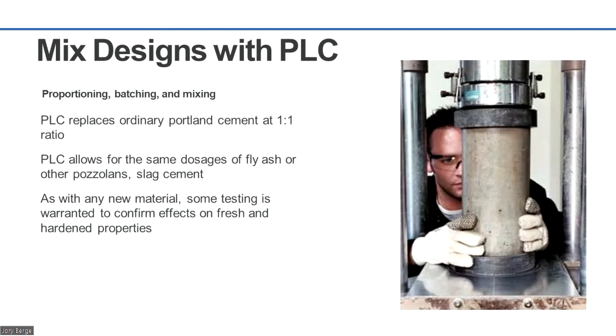And the replacement level is not like using an SCM. It weighs the same, 3.15 specific gravity. We're looking at very similar mix designs with a 1-to-1 replacement ratio. So this typically allows for the same values of fly ash and values of slag that we commonly use. So that's something to consider.